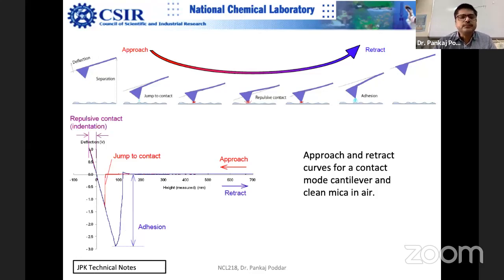Now you can see that this has made a hysteresis loop, and this larger gap or hysteresis is basically because of the strong adhesion, because you have to apply some energy to break free of it. So basically, this area under the curve is your adhesive energy. So you can calculate the adhesion actually. Now this is jump off contact. Once you break free of this adhesion, this will go above the zero force line, and then finally you have the zero force when you are quite far from the surface.